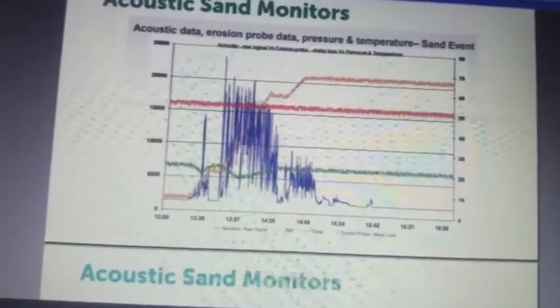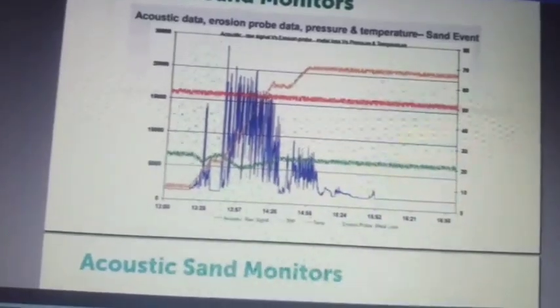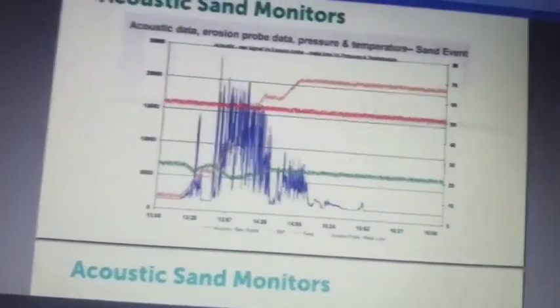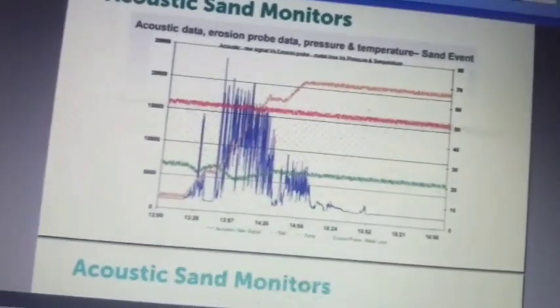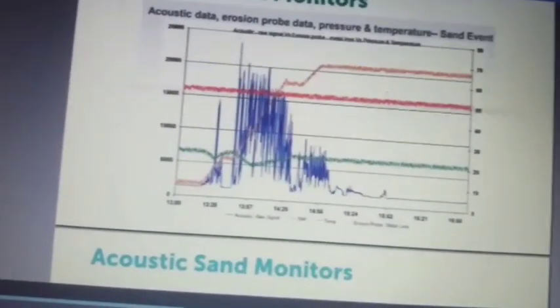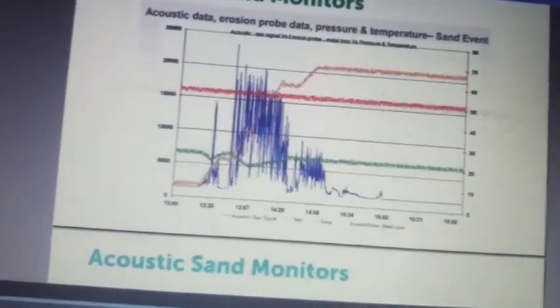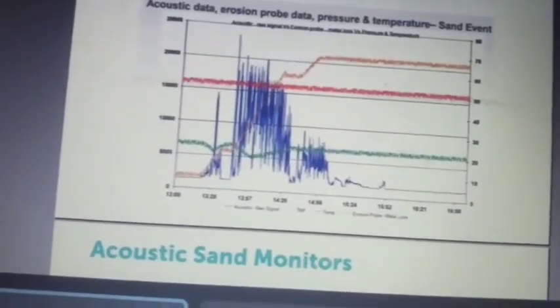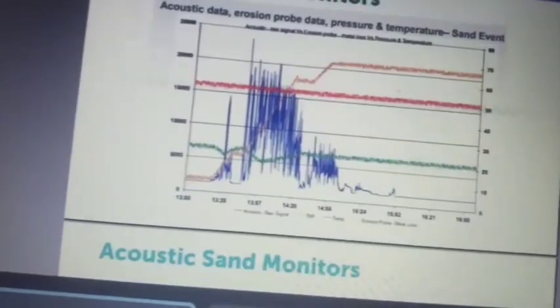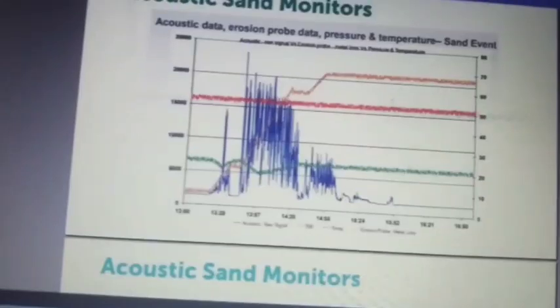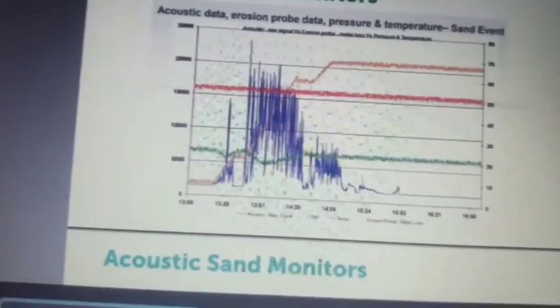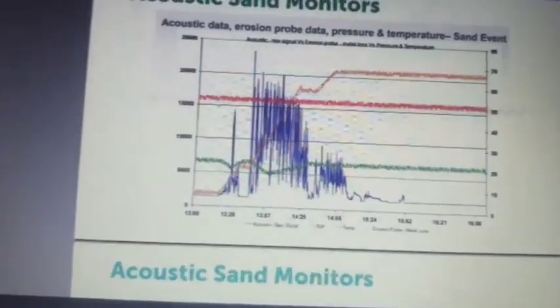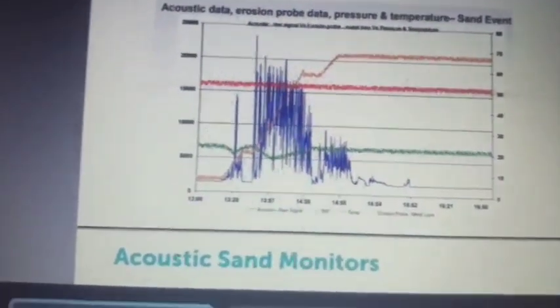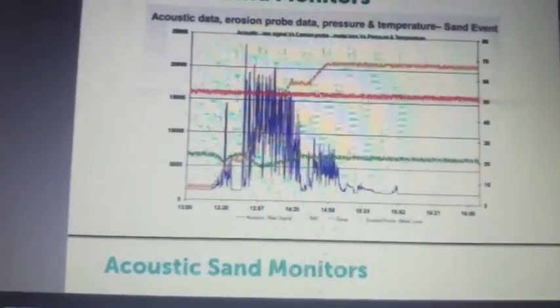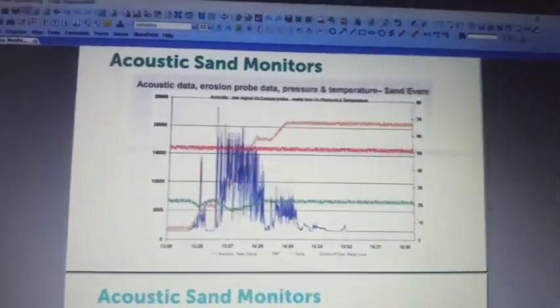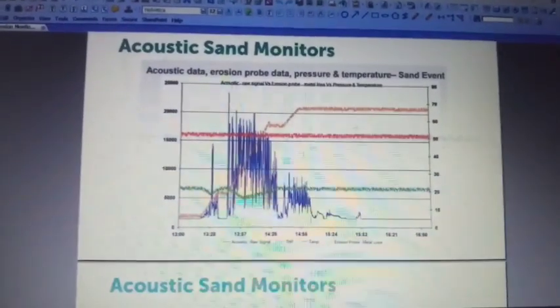Now, if you see, this is a metal loss. This erosion probe metal loss, this orange color. Initially the metal loss is low. In the event of the sand, the erosion rate increases. And when the sand loading is not there, the erosion is not there. Then when the sand loading starts, the erosion starts. And then there is no sand loading, so there is some flat region. And then again, there is some minimal sand loading, so there is an erosion rate. You can see that very clearly, that based on the sand loading, the erosion rate increases.